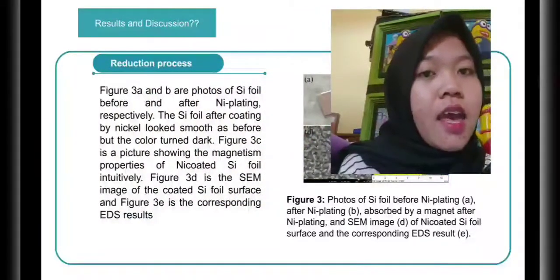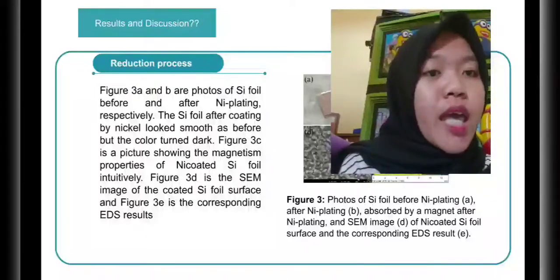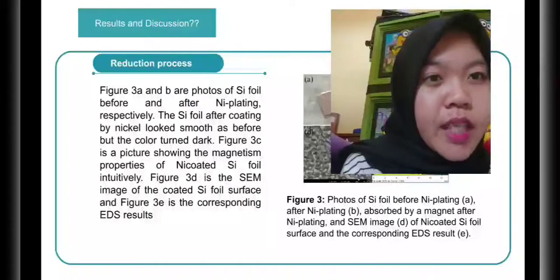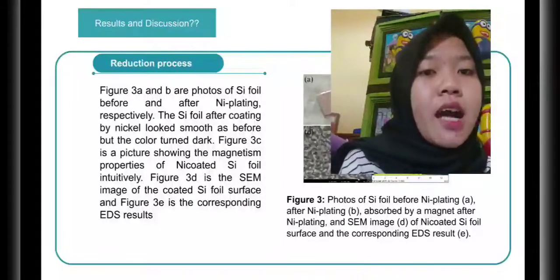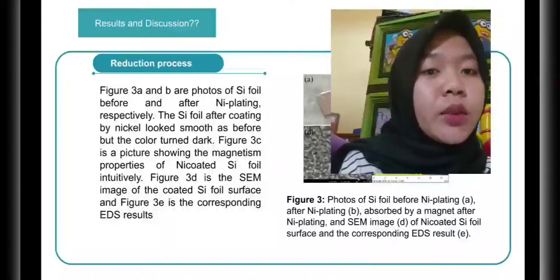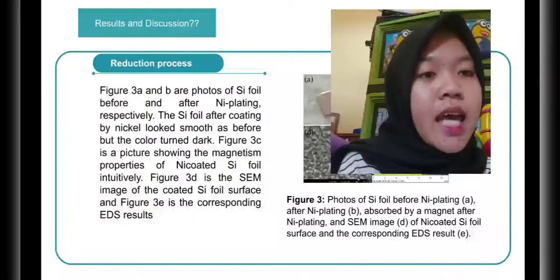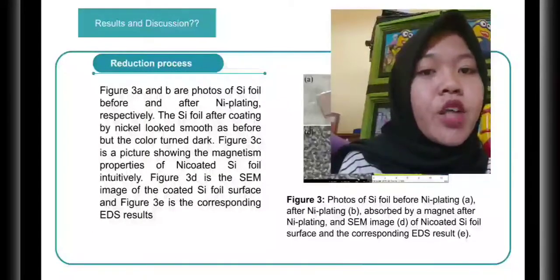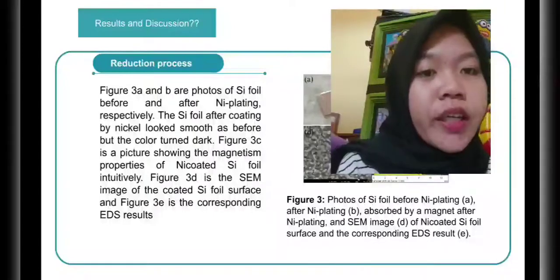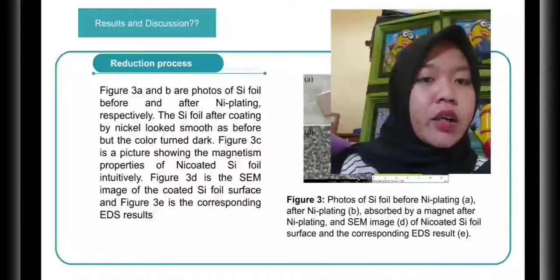Figure 3, A and B are photos of Si foil before and after nickel plating, respectively. The Si foil after coating by nickel looked as smooth as before, but the color turned dark. Figure 3C is a picture showing the magnetic properties of nickel-coated Si foil intuitively. Figure 3D is the SEM image of the coated Si foil surface, and figure 3E is the corresponding EDS result.